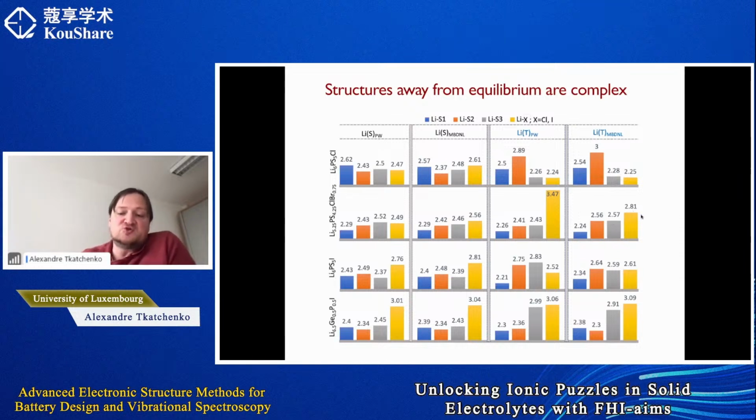It's a huge change in the geometry, which agrees with our old work on diffusion of defects in silicon, where we also observed quite significant differences in the geometry upon including van der Waals interaction. We see the same here. So basically, softer frameworks, which is exactly what happens here for this mixed anionic framework, can lead to very high changes in the distance due to the inclusion of many-body dispersion. That's quite surprising, but that explains why there are such large differences in the transition path.